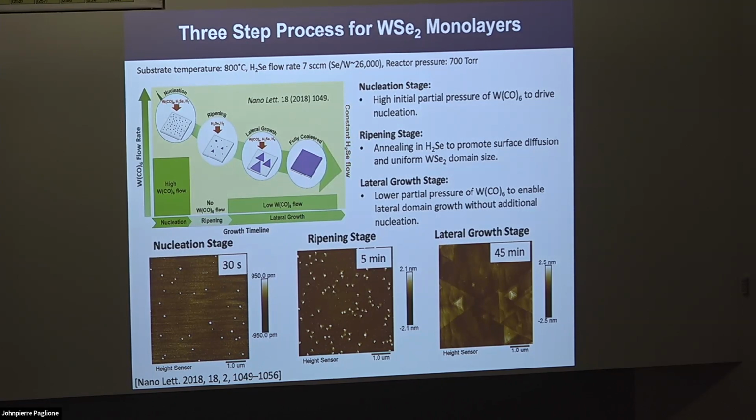Yes. I think at the beginning you showed that there are polymorphs that are different types of stacking order. Has there been work in heterostructures to mimic that, and then their properties in that? Oh, so how to make a heterostructure that mimics the polymorph? Yeah. You know, doing it bottom up is very challenging, and I talked about doping as a way to do that. At least today, there are some observations. You dope rhenium into molybdenum disulfide, you can go from the 2H stacking to the 3R stacking. So that's possible in thick layers.